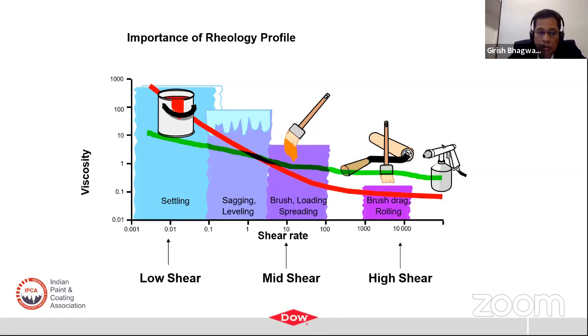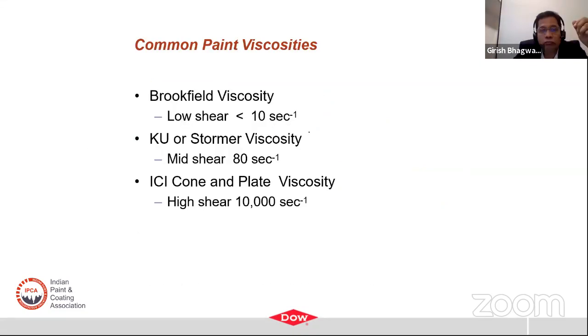So what it says is the low shear viscosity is high, but it's not so high that you will have flow and leveling issues. And the high shear viscosity is also high, but it's not so low that your film buildup will not happen. So eventually all these technical jargons have to translate from the can of paint, which is in liquid state, to a film on the wall, a more uniform film, as if you have put a sticker on the wall. That is achieved by the rheology modifiers. Okay. So anyway, let's talk of how these are measured.